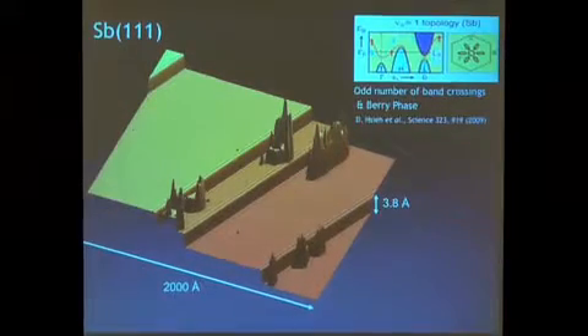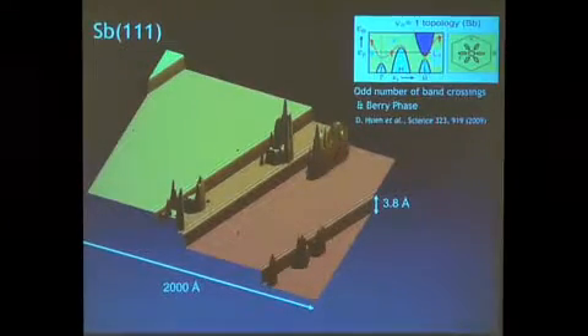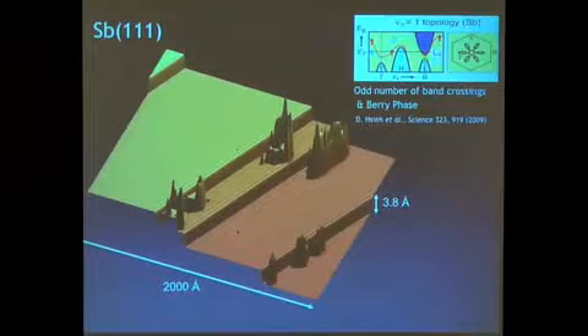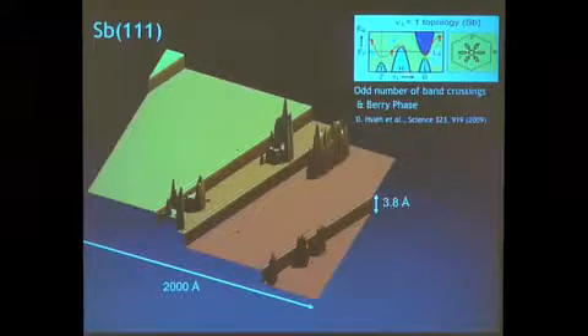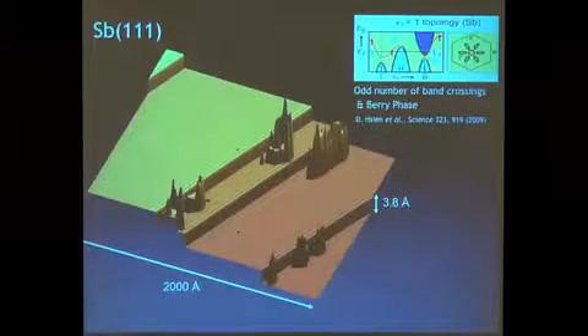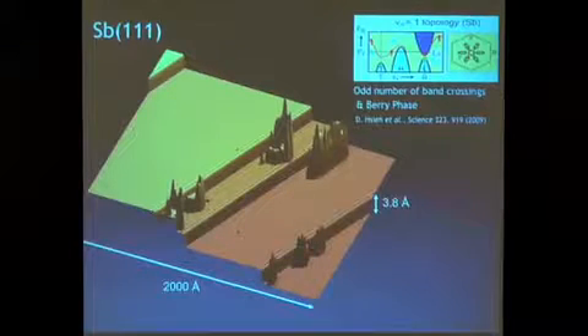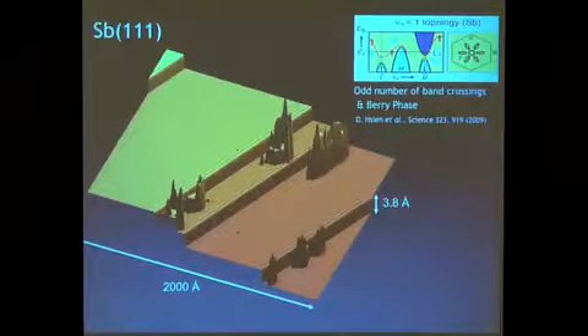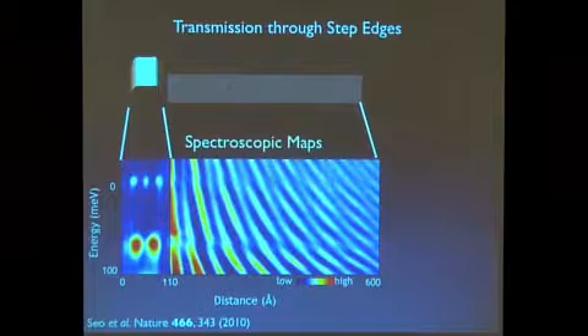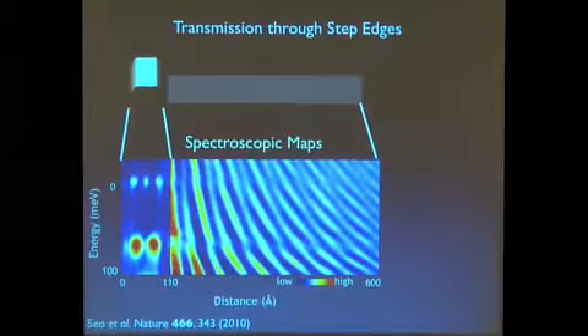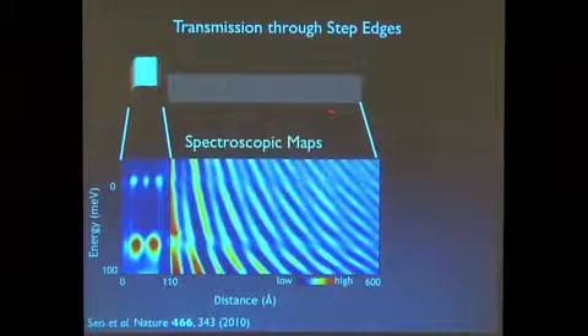So we did an experiment on antimony. Now antimony, remember, has this inversion associated with the spin-orbit coupling that I told you about at the beginning of the talk. It is a semi-metal because the conduction and valence bands overlap one another. But as far as the surface electrons are concerned, these are topological surface states. And what we did is the following experiment. We have a very large terrace and a very small one, okay, in which you're looking at electrons scattering from this small terrace.